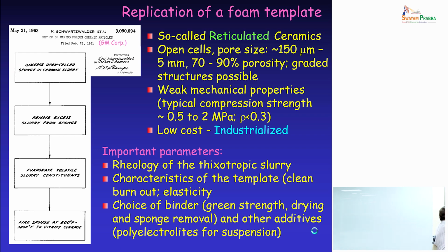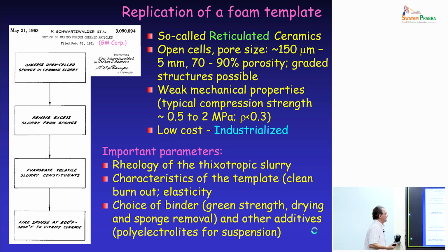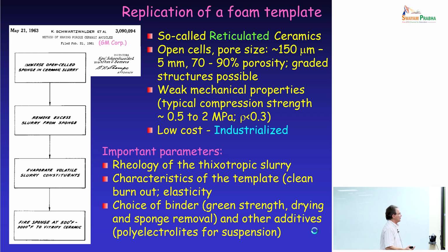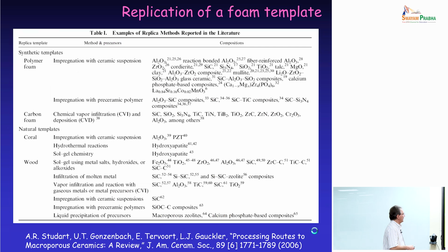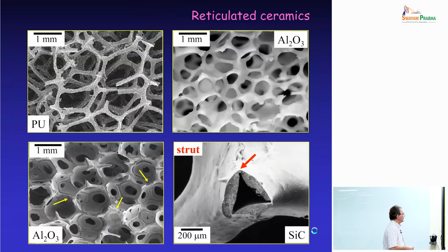And typical characteristics of these materials are that they are fully open cell. They have a cell size between 150 microns and 5 millimeters, and high porosity. They have, for different reasons, weak mechanical properties, and they are very low cost and made in large volumes. Actually, these are different types of materials that have been used for this approach. So actually, the main application is no longer with cars, because people use extruded honeycombs for that, but it is for molten metal filtration.